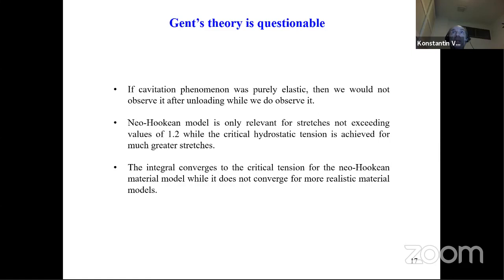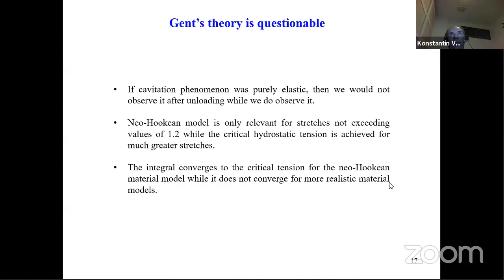While the Gent experiments are unquestionable and repeatable, Gent's theory is much more questionable on every physical assumption. First, if cavitation were purely elastic, we wouldn't observe it after unloading — but we do. Second, the neo-Hookean model is only relevant for stretches not exceeding about 1.2 or 1.3, while the critical hydrostatic tension is achieved for much greater stretches. Third, the integral converges to a critical tension for the neo-Hookean model, but it doesn't converge for a realistic material model capable of describing large stretches.